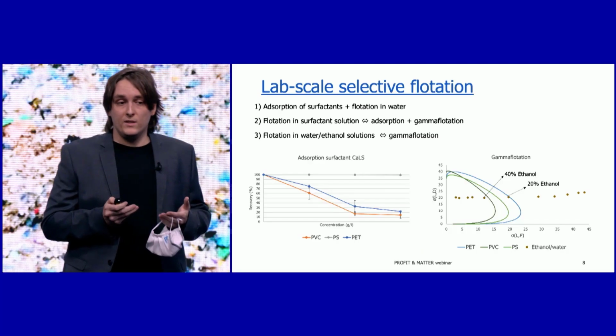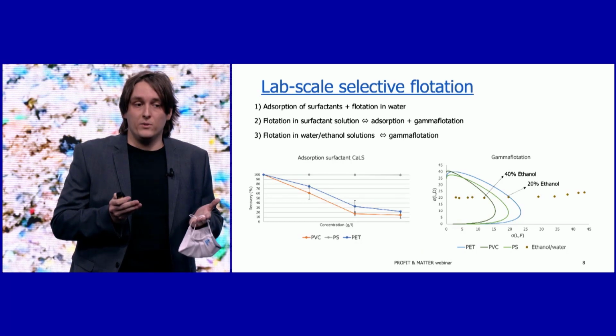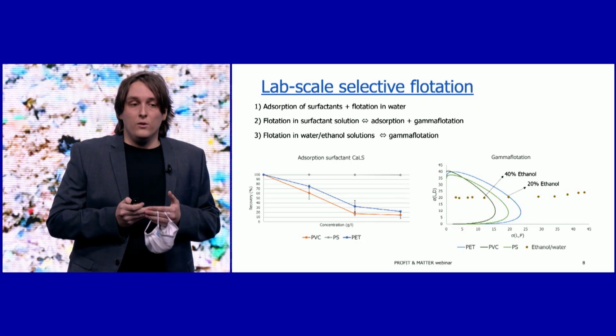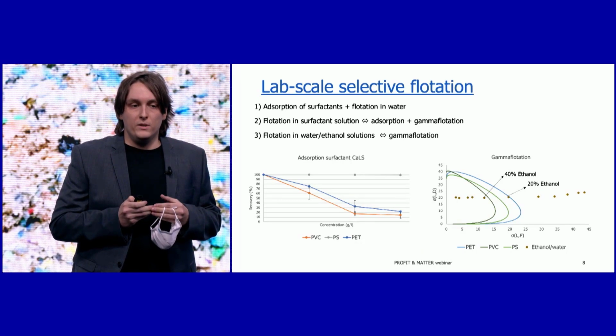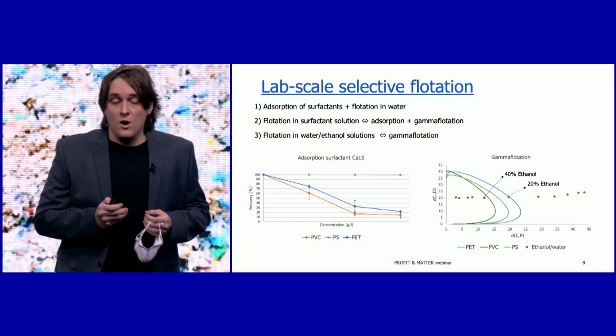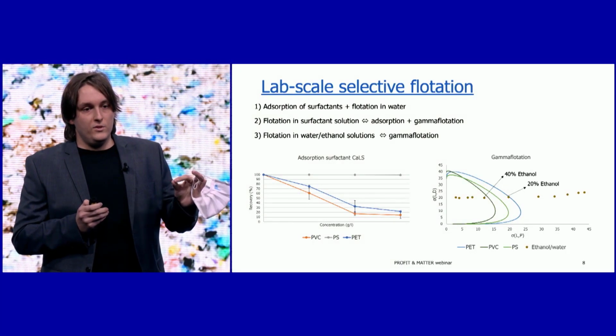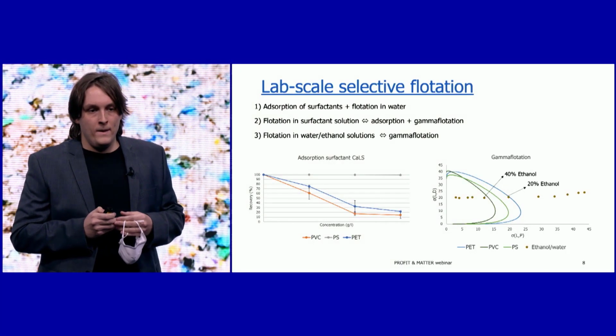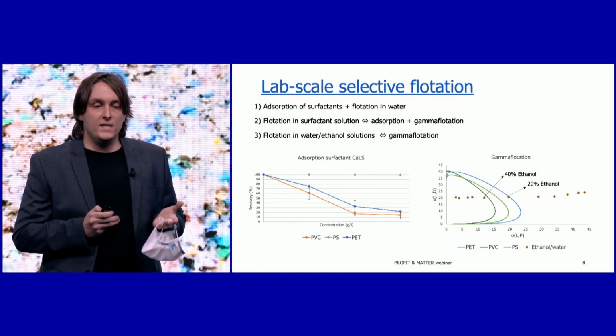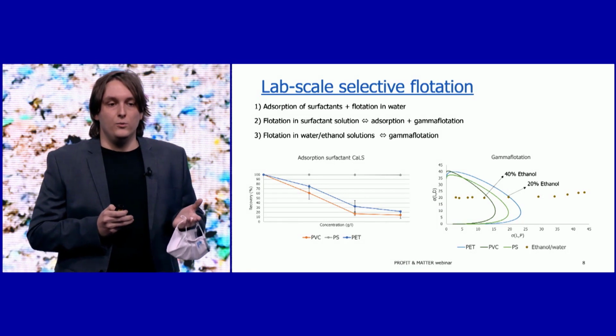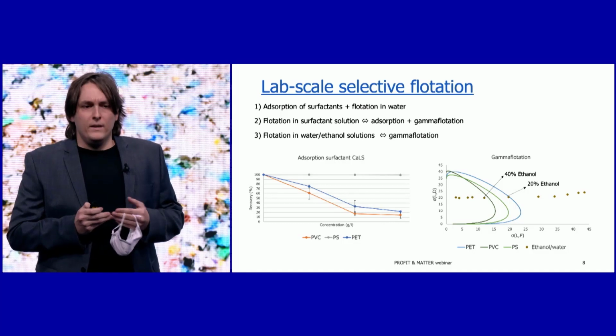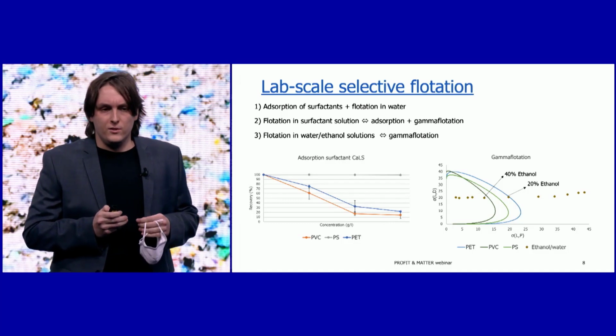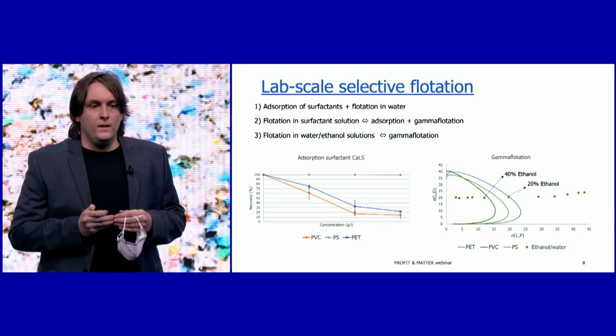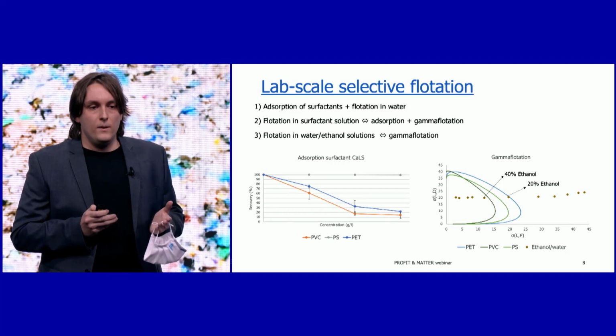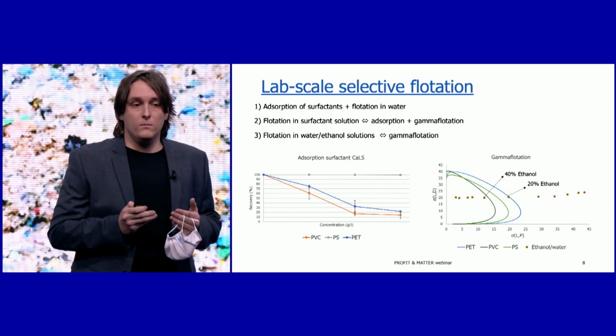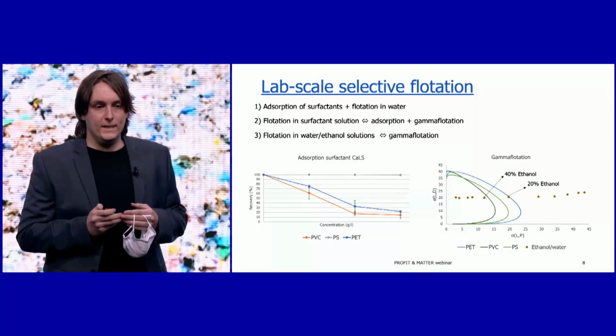A second series of experiments were focused on the flotation medium itself, because this also has an influence on the suppression of plastics. Here we did the flotation in surfactant solutions, and in this way we were able to suppress more plastics using this technique.